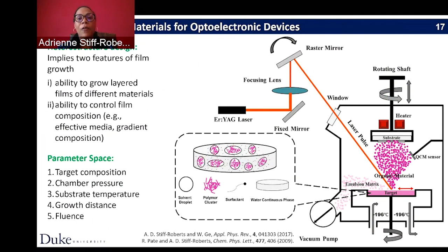But MAPLE, because of this process, is essentially a hybrid physical vapor deposition process, and it's essentially dry. So we significantly reduce the exposure of the film to solvent such that we can grow layered structures.